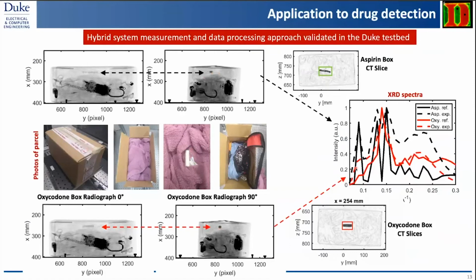But if we look at the diffraction measurements, you can see that the dashed lines, which are the spectra here for the measured aspirin and oxycodone, look very different from one another, and in fact are very similar to the solid lines, which are the diffractometer ground truth measurements that we had. So being able to distinguish between different drugs or different organic materials in this type of hybrid CT plus XRD system is one thing that we've been exploring experimentally as well.